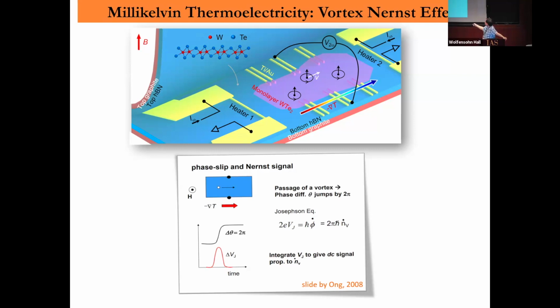If you have a vortex, it will move along the temperature gradient, and that signal will be the motion of the vortex. If the vortex doesn't move, you see no signal. The motion of the vortex is picked up by the electrode in the transverse direction. So it looks like the Nernst effect, but it's not the typical Nernst effect—it's the vortex Nernst effect.